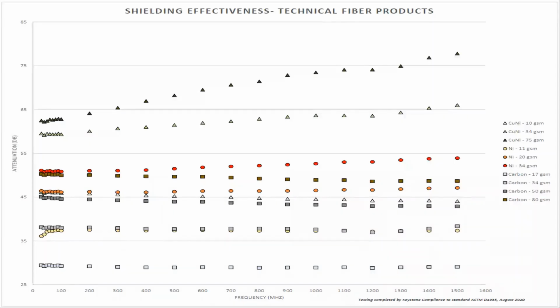So here's some ASTM D4935 testing that we've had done on our nonwovens. Here you'll see three materials: carbon, nickel, and copper nickel coated carbon veils. The carbon veils are least expensive, but also the least effective. Those are the squares on the bottom of the graph. In the middle, the circles are the nickel coated carbon veil. This is our most cost effective as far as shielding effectiveness goes.